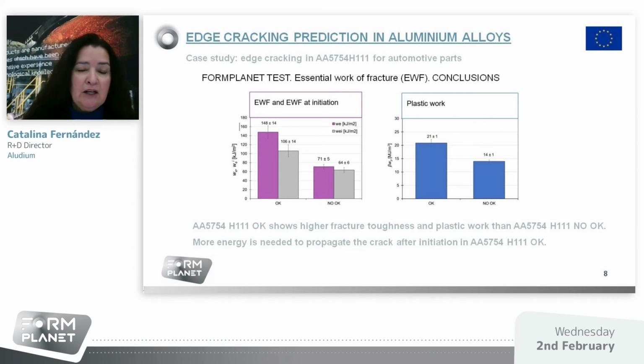Here is a graph summary of the result. The conclusion that we can take from this test, the essential work of fracture, is that the OK material shows a higher fracture toughness and plastic work than the no OK material, and also that more energy is needed to propagate the crack after initiation in the OK material.